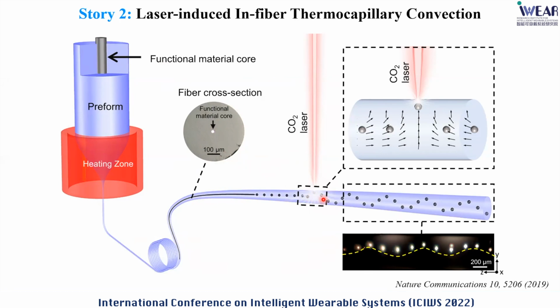After we get those spheres, we continuously heat up this section, and we want to induce a localized surface tension gradient. When we have the surface tension gradient and a sphere under this laser heating region, due to the surface tension, the sphere will move towards the direction of the laser heating. So simply by adjusting the direction of the laser heating, we can manipulate the position of single semiconductor spheres inside the fiber.